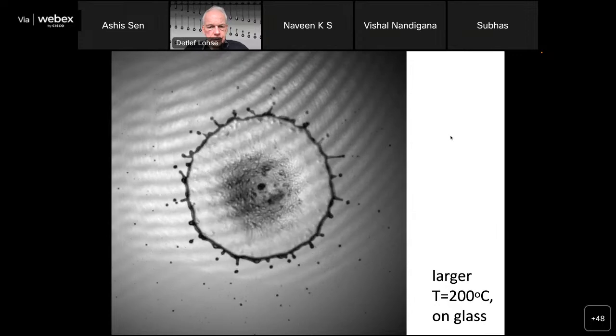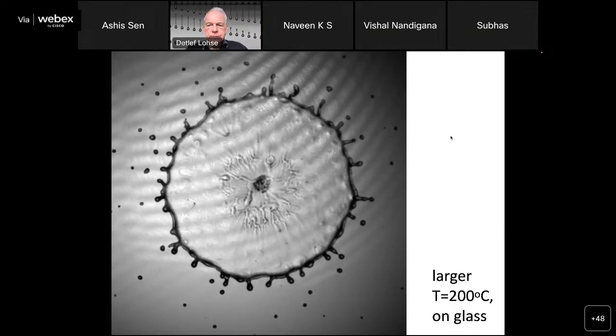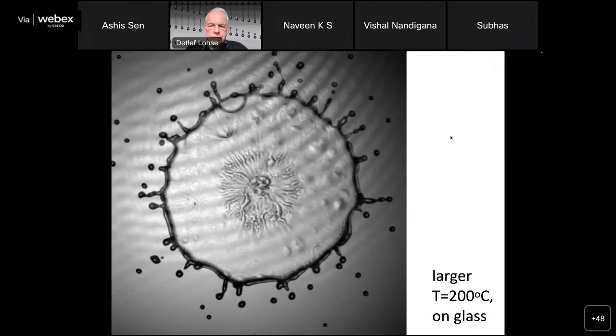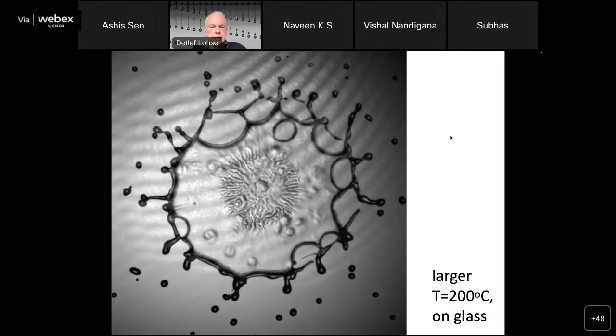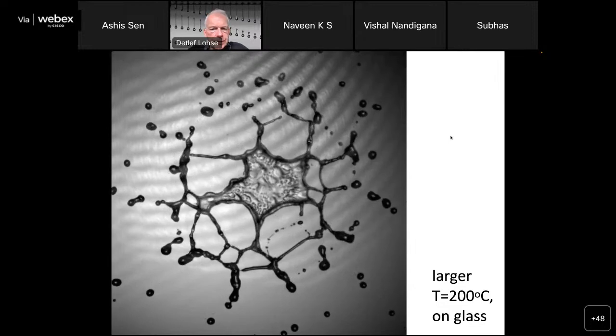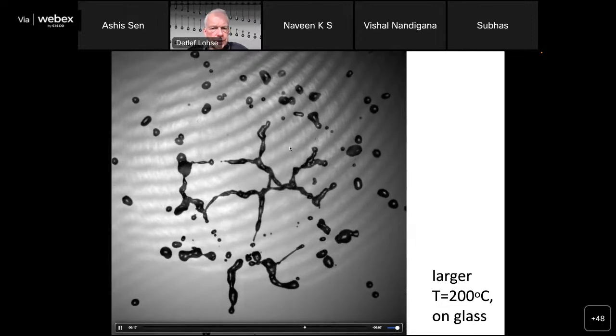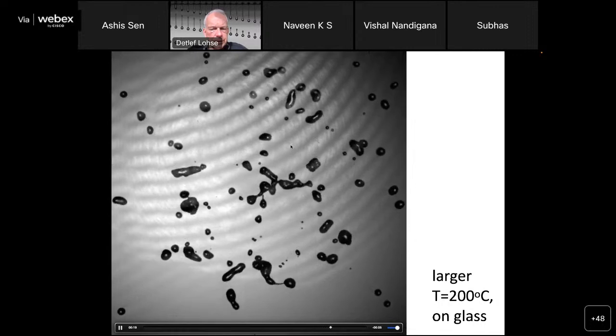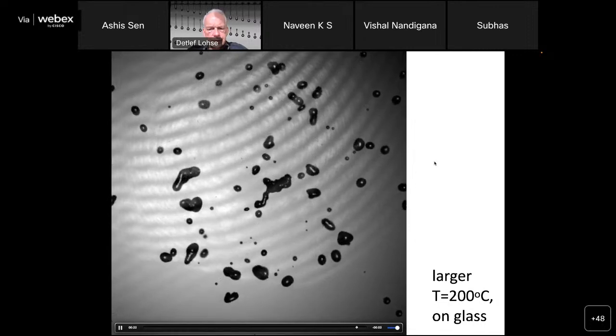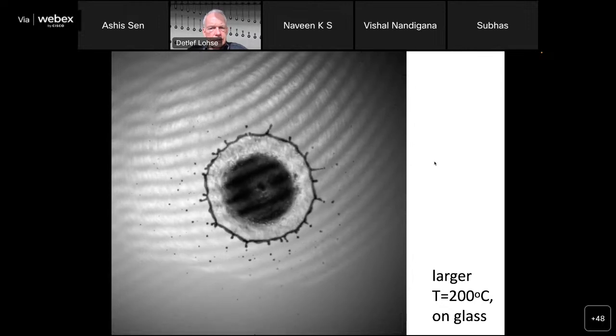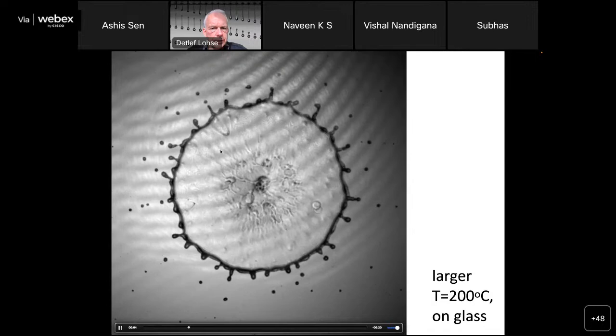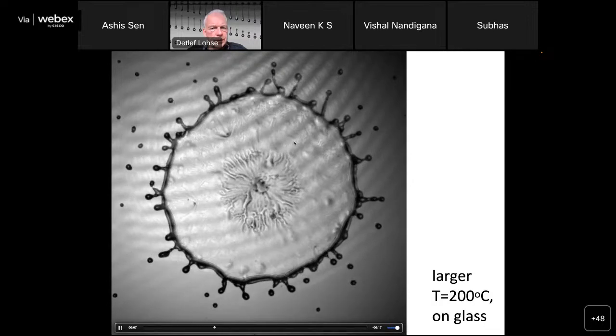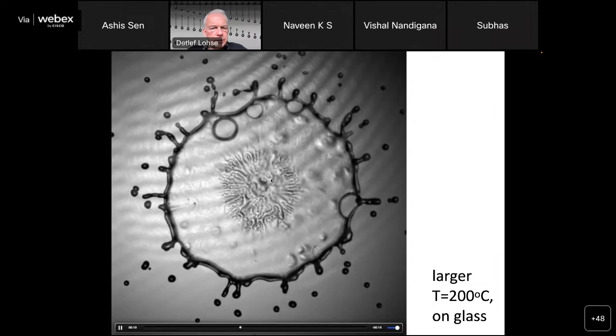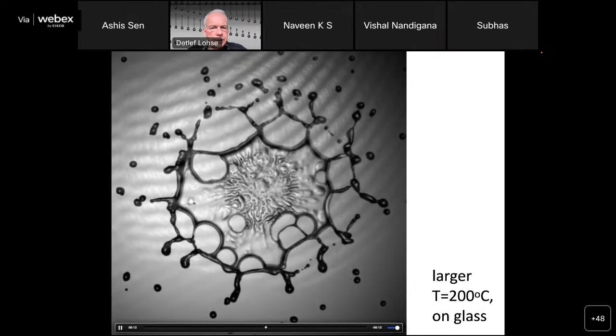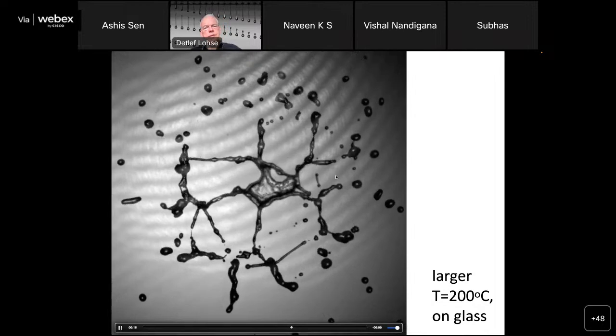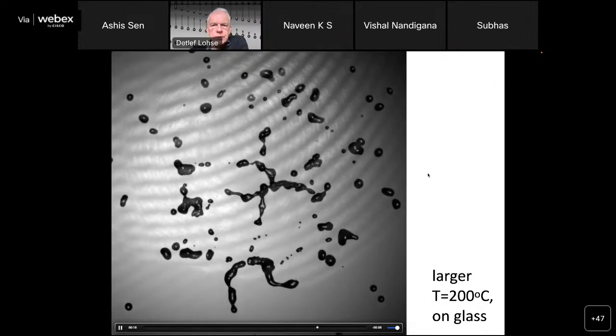Well, here some other examples. So now we have the droplet falling on glass. And what you get is this thin film of liquid, and this thin film then breaks. So you see here all these droplets emerging. So first, when it falls down, so this will play again, it spreads. So here you see the spreading, and you have this thin film. It breaks, so here bubbles form, and then you have this Taylor-Culick retraction, and you end up with these droplets.